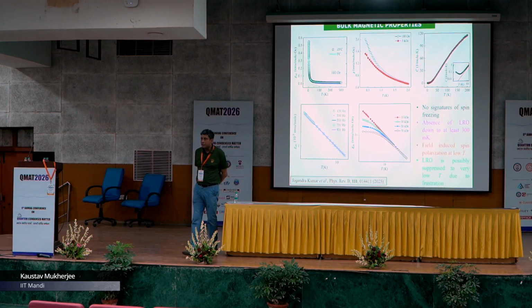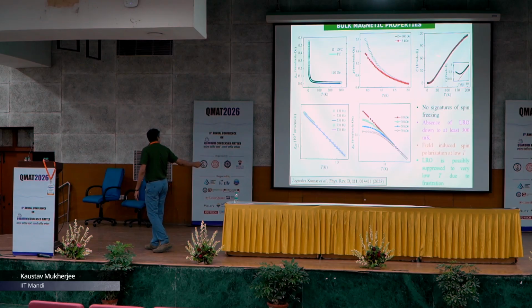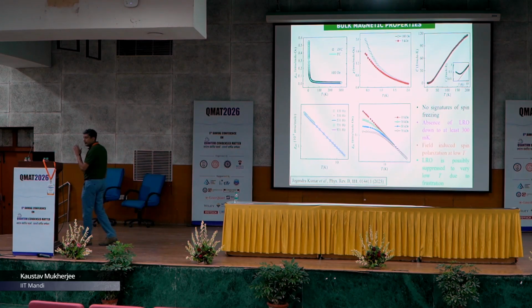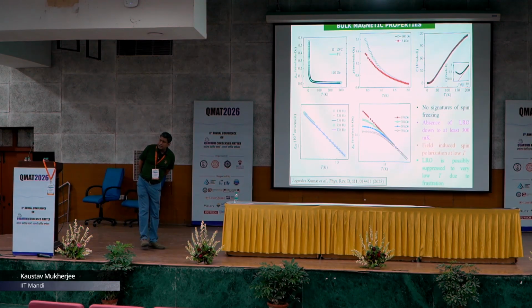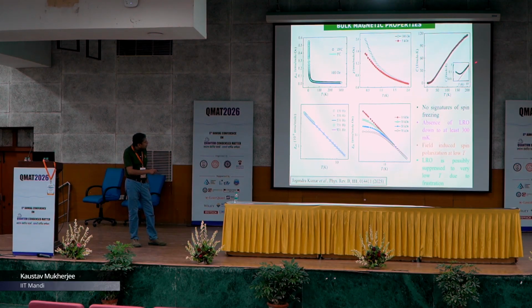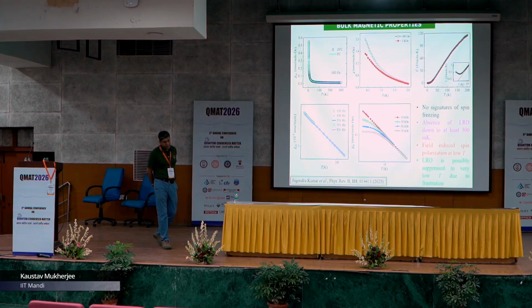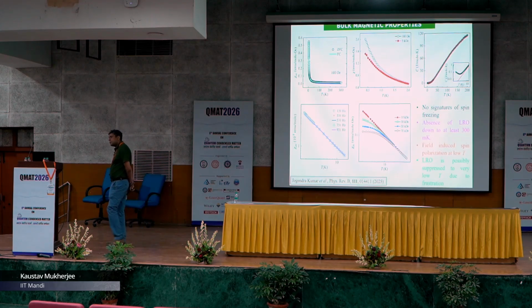We also did a thermodynamic measurement down to 1.8 Kelvin, which is shown here. This curve is also smooth and no anomaly is observed, which is in analogy to our magnetization curve. We tried to fit this heat capacity curve using a combination of Debye and Einstein models. The data fitted well at higher temperature, but as you can see in the inset an upturn is observed and the fitting also deviated. This upturn is possibly arising due to a Schottky anomaly, because what we saw, and I will also show later, is that under the application of magnetic field the upturn changes into a peak and the peak temperature increases with the increase in magnetic field.